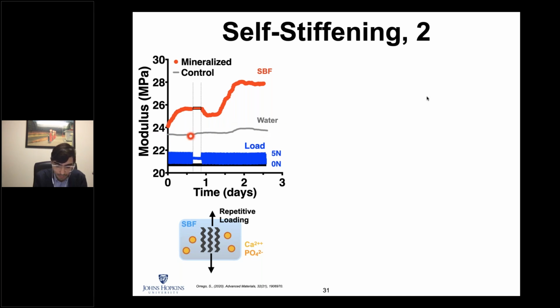Whereas if we do the same test but for water conditions, solutions without calcium, we pretty much see a straight line on the modulus. There is no real change of modulus. So this is very exciting.